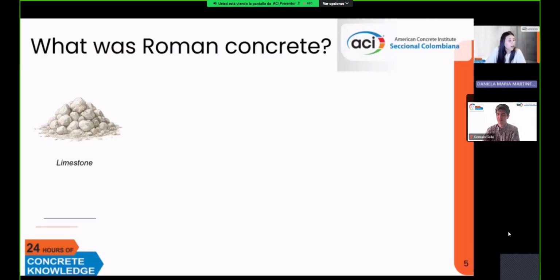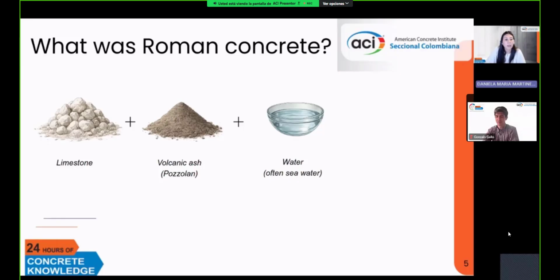Roman concrete consisted primarily of limestone, which is one of the main ingredients, the raw materials that we use today in our modern Portland cement. And this limestone was also heated to a certain level to obtain quicklime or hydrated lime, like we normally do with our modern cement. But this product was also mixed with volcanic ash, which is a pozzolan, and mixed with water to form a mortar. And this water was often seawater. And this Roman mortar was then further mixed with big chunks of fragments of rocks or rubble from debris from other demolition sites or construction. And this massive concrete was what was used in Roman infrastructure.